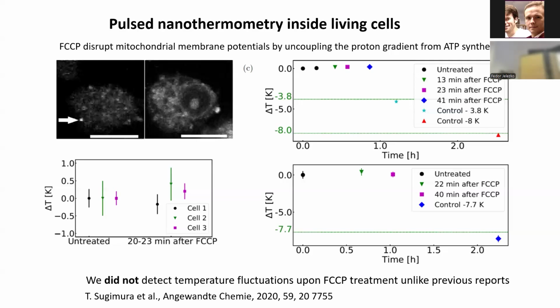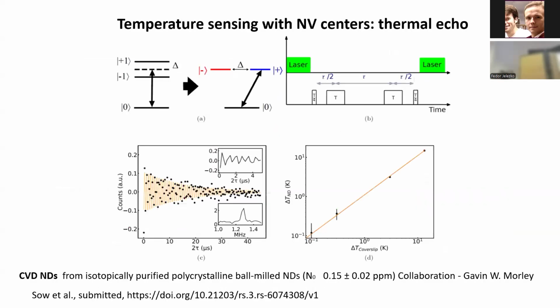Question here on the thermometry. The NV fluorescence is also somehow reacting to pH, right? With some charge state change? The charge stability of NV can be affected by pH, yeah. But here you would just get some change in contrast. If the NV is in an NV0 state, it doesn't contribute to an ODMR signal at all. We will just reduce the contrast, but it won't affect the spectra at all. It will be just lower contrast.